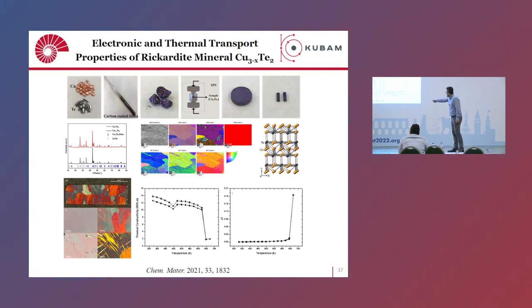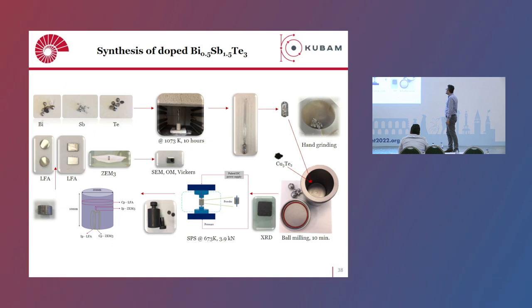At low temperature, this shows a metallic character, which means the ZT is almost negligible. After this transition, you can see that suddenly the ZT goes up quite a bit. Still low, around 0.2, but it is promising. Now, as a copper source, or for its metallic nature, we put this material in bismuth antimony telluride. We prepared the bismuth antimony telluride by solid state synthesis, ground it, put it in a steel vial, added copper telluride, and did XRD analysis, SPS, LFA, and all the other transport characterization.